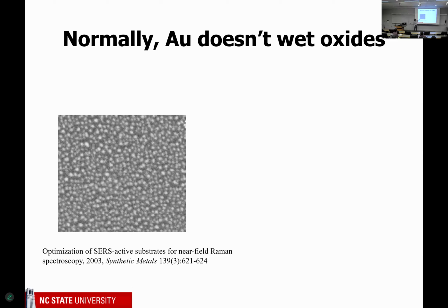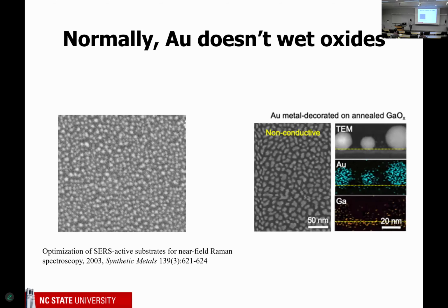These little white spots are gold, and there's no way that this is going to be conductive, because if you try to apply electricity through this film, there's no percolated pathway. So that's bad news. And in fact, if you deposit 4 nanometers of gold on gallium oxide, you end up with little islands. And if you look at a side view, those little islands look like little dots. So that's gold, that's gold, that's gold, but they're not connected. So it's not going to be conductive.